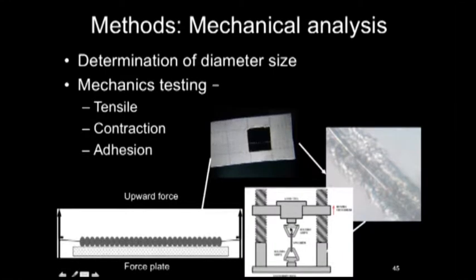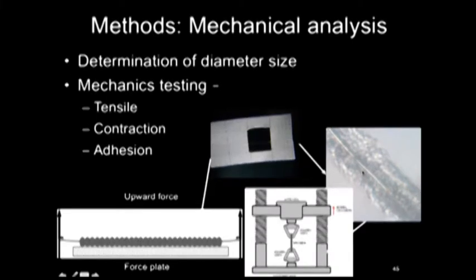And as we pull up and pull off on the force plate, we would then know how far the thread is extending and how much work is being performed, how much energy is being absorbed during adhesion. And we would also then, using separate threads, measure tensile properties using methods that are the same as I described before. And we would also be determining diameter size. And this is a thread that's been pressed onto a glass slide, so we can measure the diameter directly.